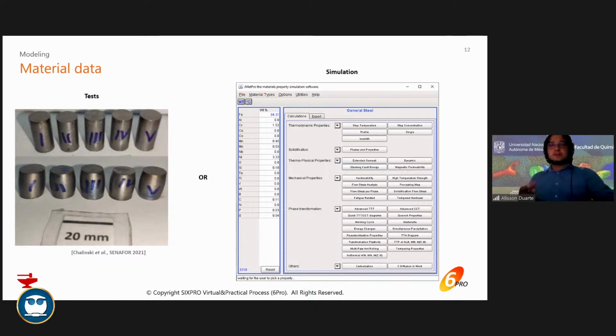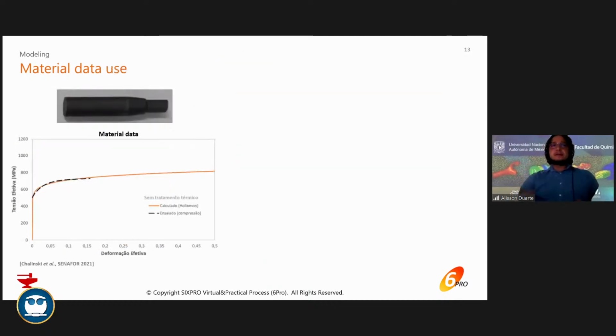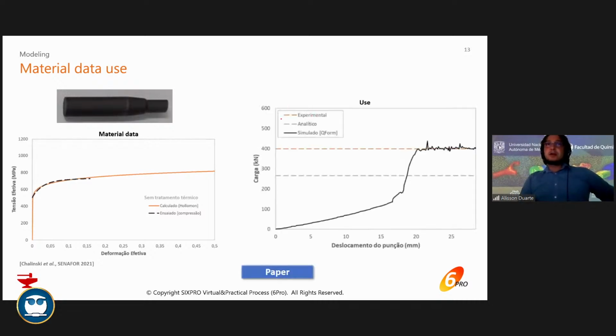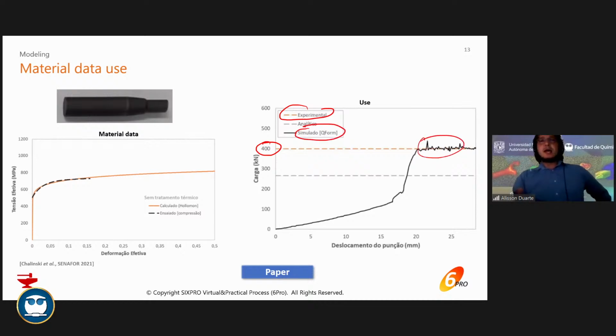So material is really important, of course. And here, from these, we got, for example, the flow stress data. So you have this experimental, and then from the experimental, you get this complete curve in order to simulate. Then we simulated that, and you could see that in the experiment we had around 400 kilonewtons press load, while simulating this, we got pretty close. It's a real case, and it was very important to define before doing the experiment. This is one of our customers as well.